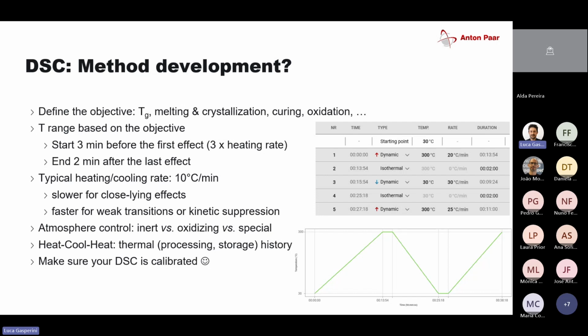How to calculate that? That's quite easy. It's 3 times or 2 times the heating rate. So if I'm heating 10 degrees a minute, 3 times the heating rate, 3 times 10, 30, I need to start 30 degrees below the first expected effect.